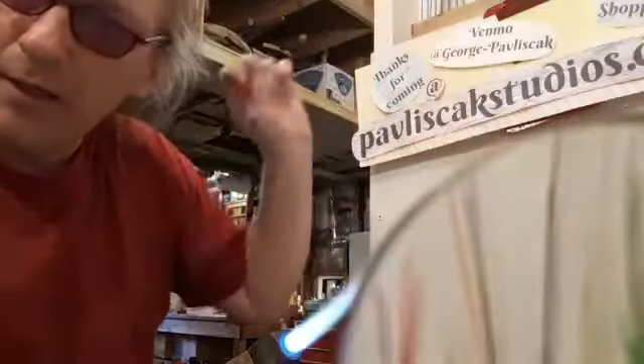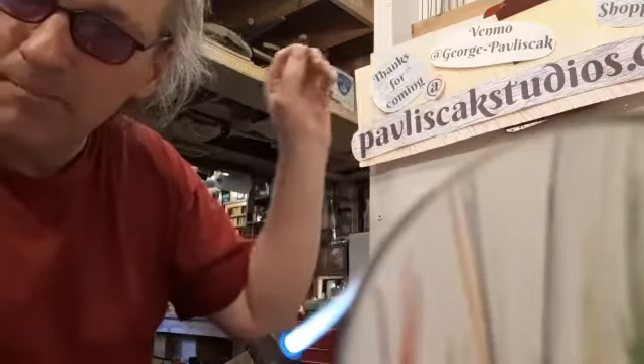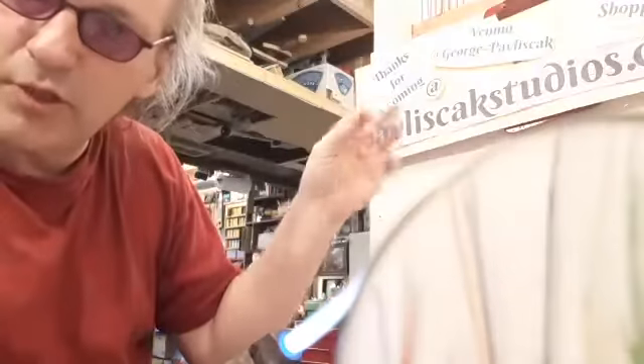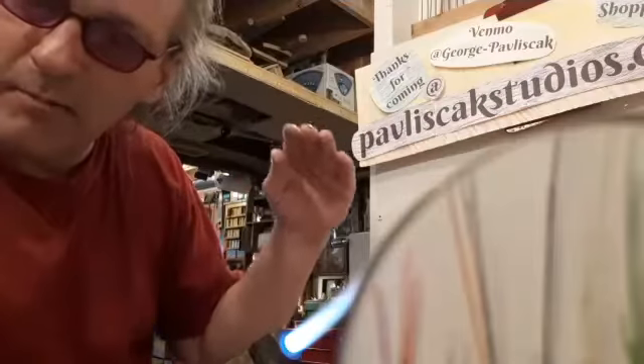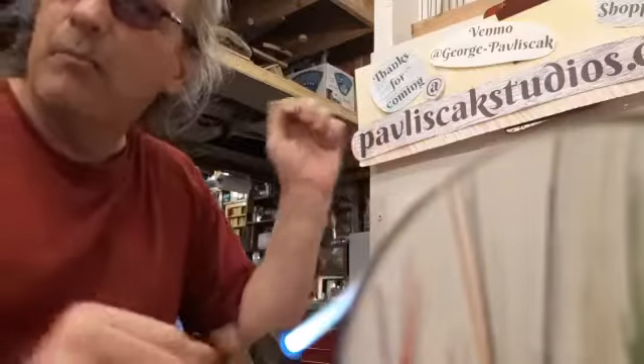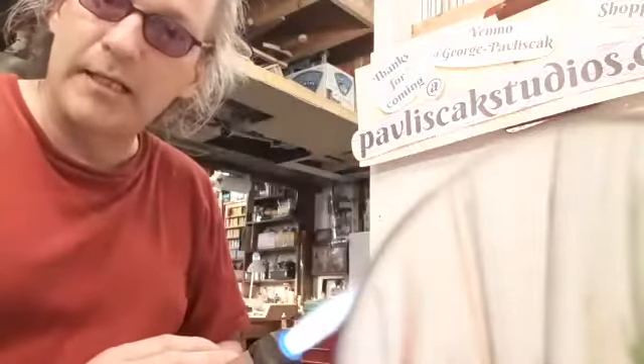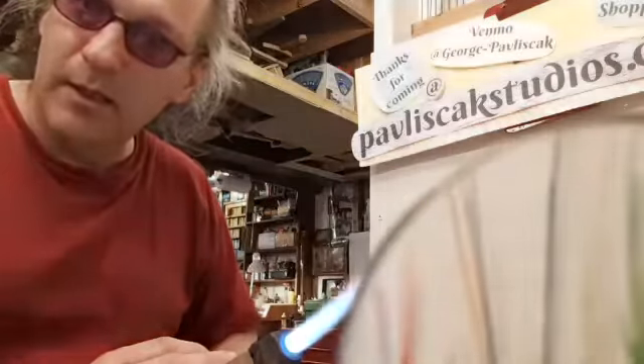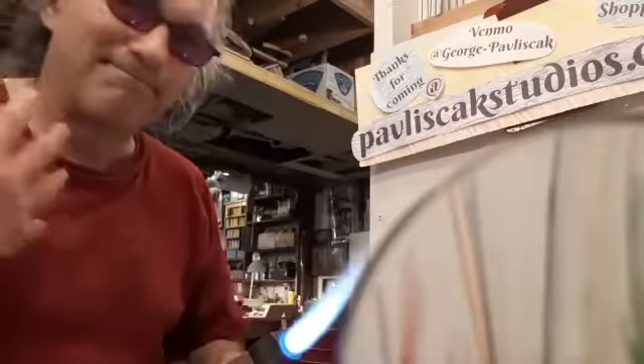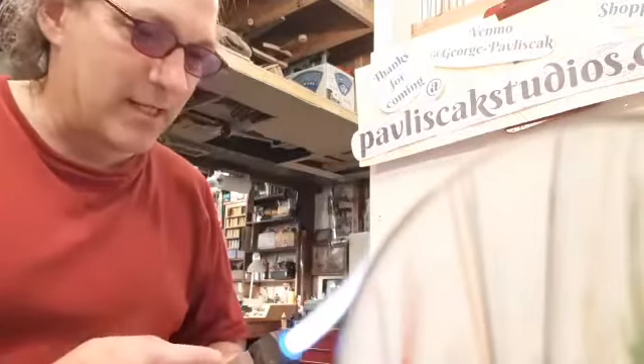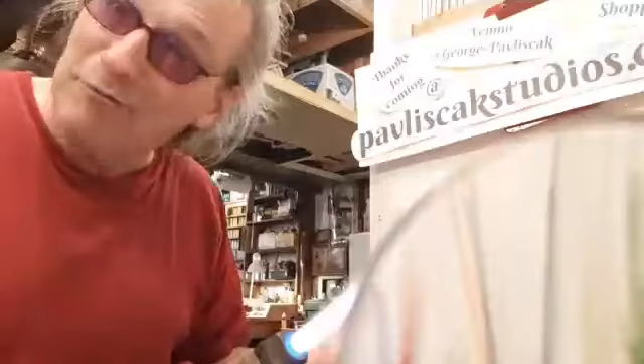So there's a high side gauge which you turn on. High side gauge gets pressurized. Then you have an adjustment which you can adjust the pressure of the gas that's coming out of the low side of the gauge. And that is where I adjust my 8 psi for the torch. And then this adjusts volume on the torch. It goes from 0 to, I'm not sure how many liters per second the flow is allowed out of this torch. This is a mid-sized torch, so I'm guessing a medium amount.